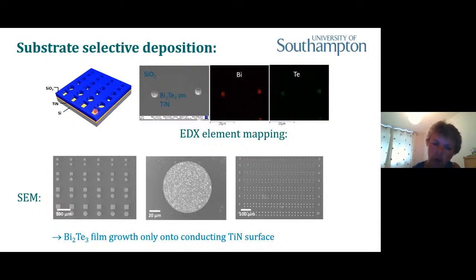So this is unusual for CVD, that we're getting this very high substrate selectivity, and you can see that reflected in some of the figures at the bottom, just showing that you get really beautiful arrays, quite an unexpected degree of selectivity by controlling the quantity of precursor we use, so that we supply enough just to fill the titanium nitride region and not to coat the insulating silica region.